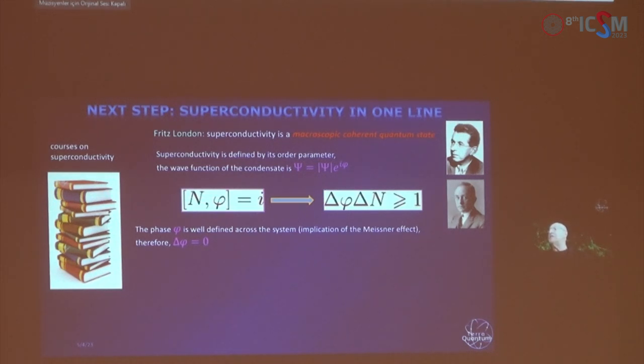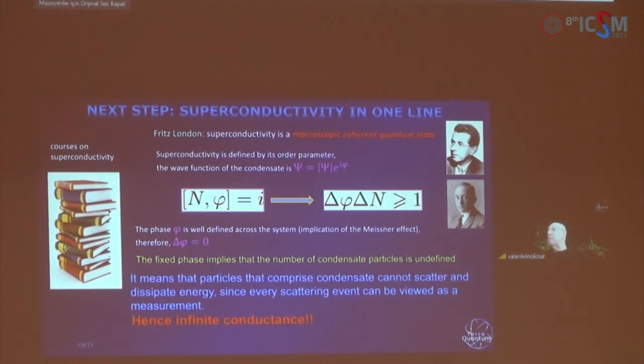Since we know from the Meissner effect that the phase is well defined across the system and is basically a constant, the uncertainty in the phase is zero. It immediately means that the uncertainty in the number of particles is infinite. They can fluctuate however they want. But then it means that particles that comprise the condensate cannot scatter and dissipate energy, because every scattering event can be viewed as a measurement, and it would give us an opportunity to count the particles, which is not possible. And therefore, scattering is not possible, and we should have infinite conductance. This is our understanding of superconductivity in one line.